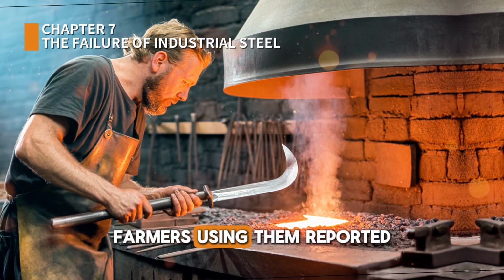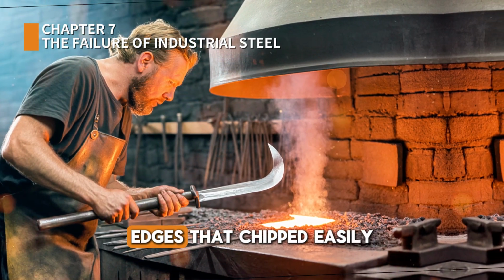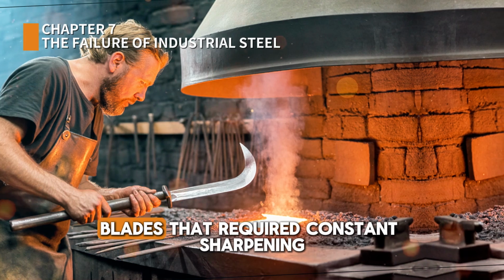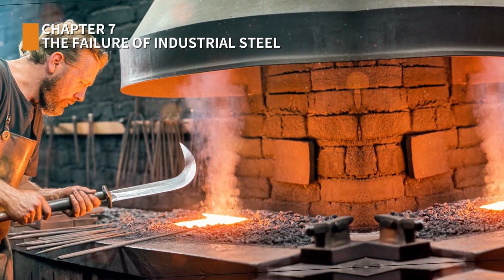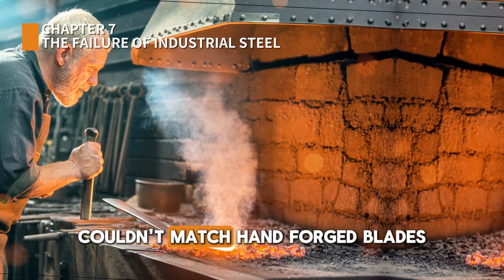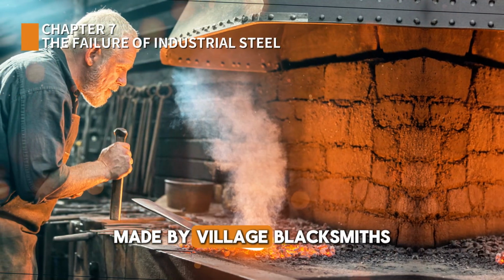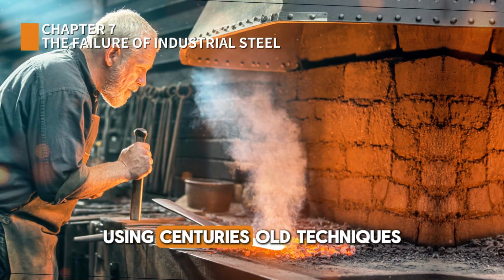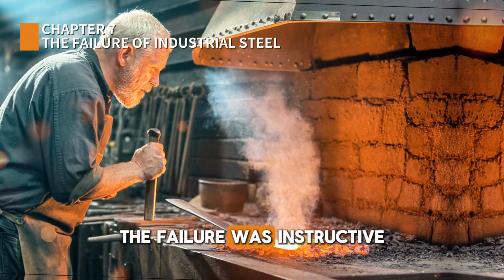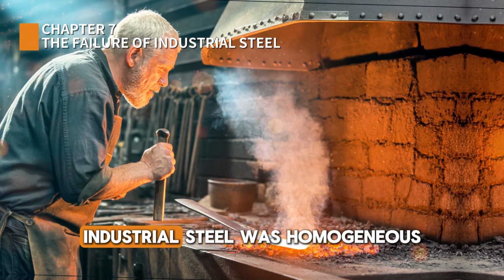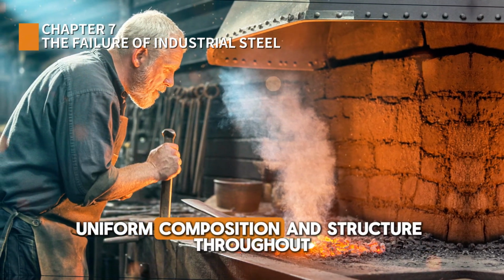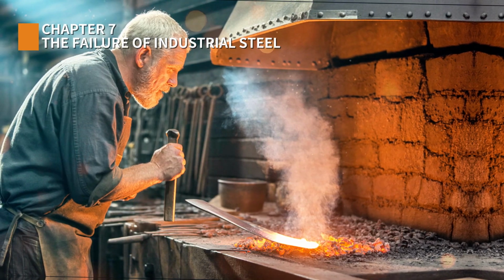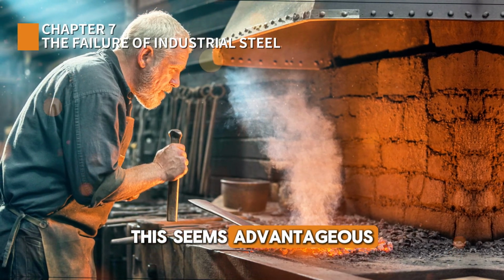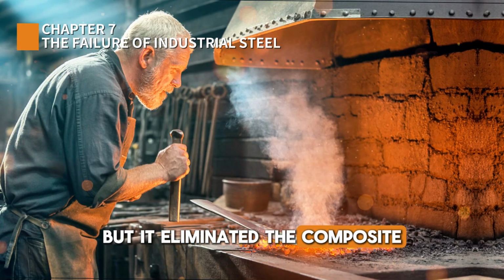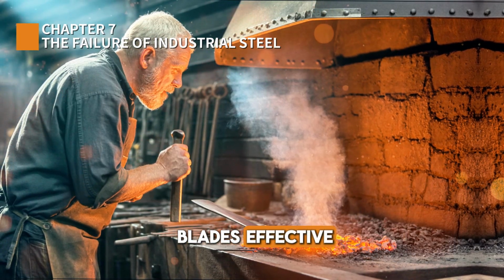The industrial scythes failed. Farmers using them reported rapid dulling, edges that chipped easily, blades that required constant sharpening. The industrial products couldn't match hand-forged blades made by village blacksmiths using centuries-old techniques. The failure was instructive. Industrial steel was homogeneous, uniform composition and structure throughout. This seems advantageous, but it eliminated the composite structure that made traditional blades effective.